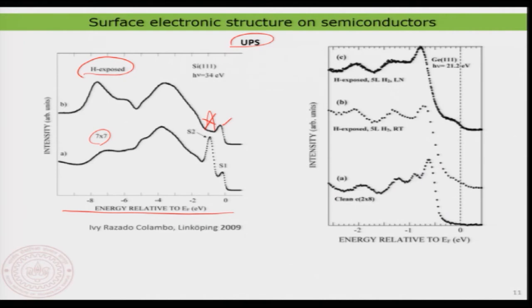Now, you can use this kind of spectroscopy to look at the surface and understand what kind of chemical change has gone on, and where specifically it has happened. Of course, our understanding is better now because we have used scanning tunneling spectroscopy and photoelectron spectroscopy to clearly differentiate where S2 and S1 are coming from. Originally, before scanning tunneling spectroscopy, it was not known where S2 and S1 originate from, but now we clearly know it. And a combination of this kind of spectroscopy gives you huge and very useful information about the interfaces and the surfaces themselves.